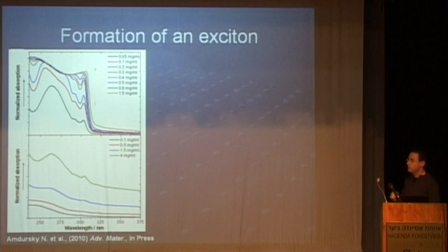This peak highly resembles the absorption peak of quantum dots, which is a peak-like absorption spectrum. And we can see that as we increase the concentration, above a certain concentration of 0.4 milligram per ml, I receive the peptide nanotube formation and the hydrogel formation, and the monomer peak is completely disappearing, and from the small peak we receive a step-like absorption spectrum. So we can really follow the dynamics of the creation of the structures from a small nucleus, which looks like a quantum dot, into a full structure which looks like a quantum well. The bottom curve is my negative control. It's exactly the same molecules, only in a condition where I cannot form any nanotubes.